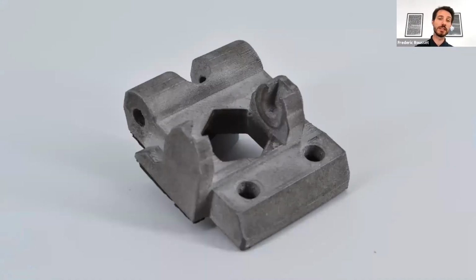And this is the same for this one. This one, we didn't even try to do it at 0.6. We knew that the part is quite big and heavy. It was a very heavy part. So we put it around 1.2 liter per minute at first, and the part got out of the furnace very well. So the solution is working very well for now.